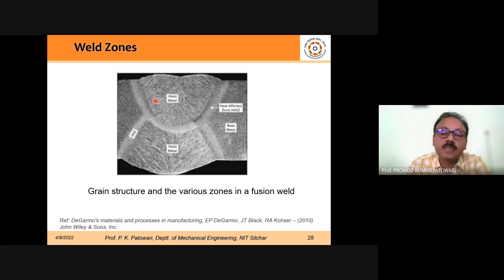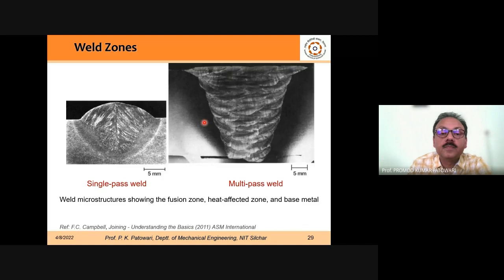If you look at this diagram, you will find that this is a photographic view of the microstructure of a welded joint. It can be a multi-pass or two-pass material. So this is weld metal, these are the base metal on both sides, and you can see the heat affected zone in and around. This heat affected zone makes the joint sometimes weaker. There can be weld zones with a single pass, there can be multiple passes. And you can see here the nearby area is being affected. So this is just a microstructure of a welded zone.